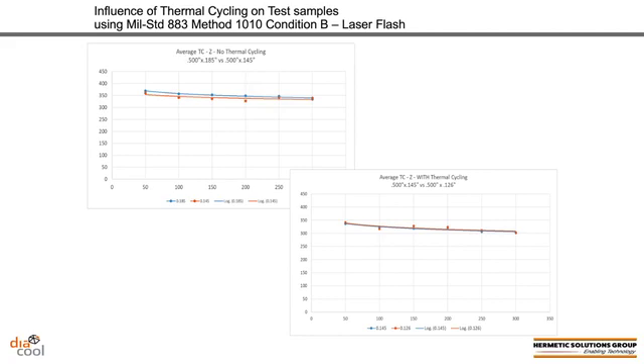But you can see here in the chart on the top left, I took substrates of this material and tested them from 50 degrees C up to 300 degrees C with no thermal cycling. And you can see the material sits in that 350 watt per meter K range over that temperature range. Then I took those products and thermal cycled them using conditions like Mil Standard 883, Method 1010, Condition B, for 60 cycles and then tested the material again. And that's depicted in this chart down on the lower right.